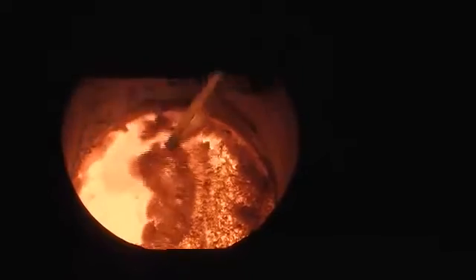Our steel casting machine of the SGA series with a melting capacity of 25 kilograms of steel can be used for steel, stainless steel, nickel and cobalt-based steel like Inconel. After only a few minutes, the metal starts to change color and melts. Skilled casters can read the temperature of the metal from the color red to white. Equipped with suitable protective clothing and the metal at a temperature of more than 1700 degrees Celsius, a binding agent is spread on top of the melt and the slag is manually skimmed.